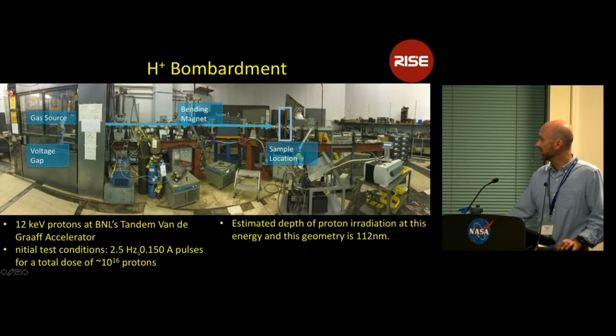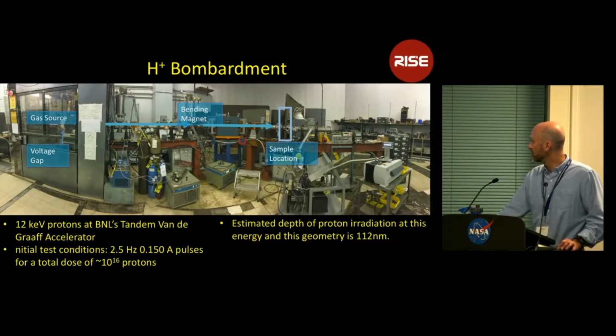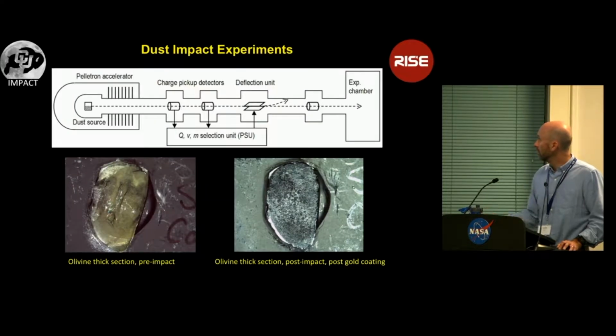Our initial tests were done at these conditions, and we end up with a total dose on our samples of about 10 to the 16 protons. And we estimate for the energy of these protons that the estimated depth of penetration is about 112 nanometers. We did our dust impact experiments at the Colorado Impact facility using their particle accelerator.